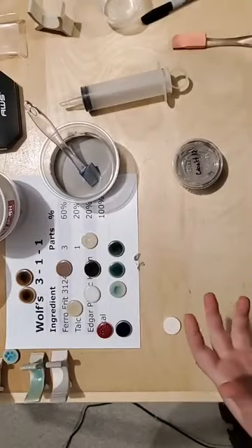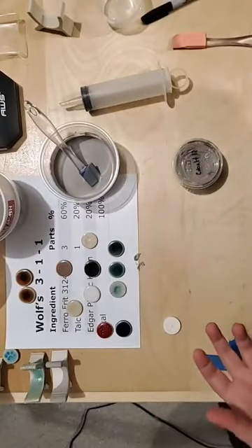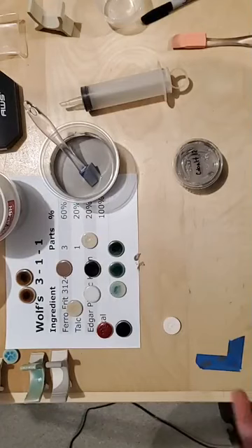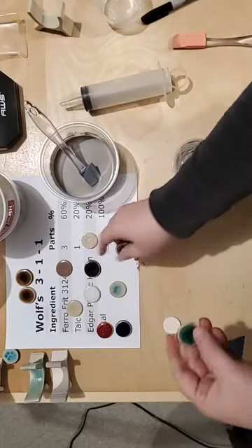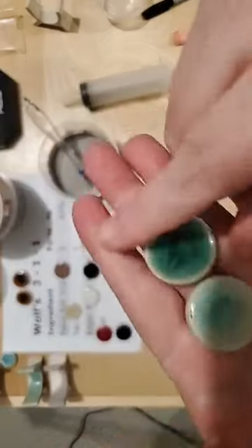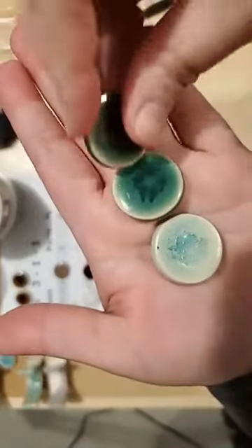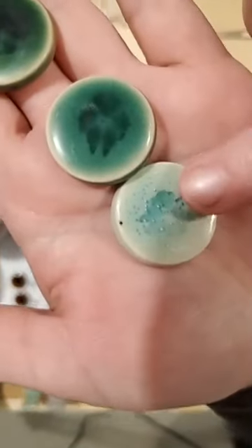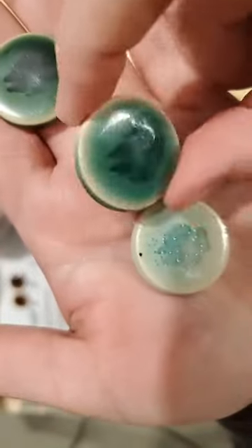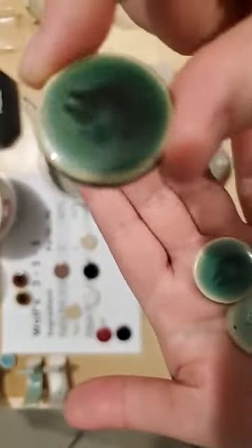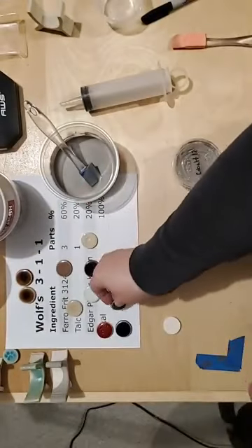So it's all about the different materials being refractory or being a flux, and so you kind of have to adjust for that when you have your whole recipe out. You can see how different, like the copper too. The more copper that you get, the more the bubbles cleared. So you have 0.5% with these bubbles, 3% with these bubbles, and then by the time you get to 5, the bubbles are almost gone. So, you know, it's all about the melt and the composition.